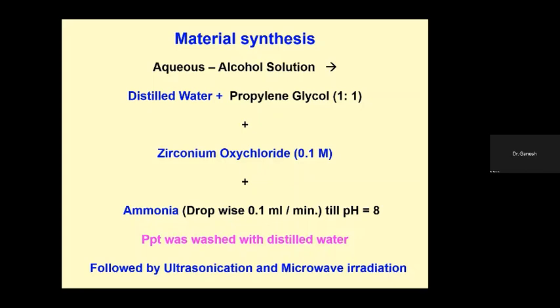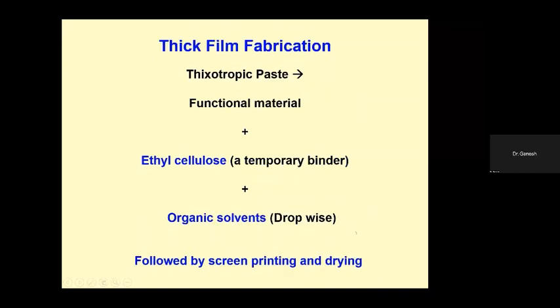If we perfectly manipulate the pH and the concentration of the solutions, then we can get different forms of nanomaterials: nanorods, nanoplates, nanoflowers, nanopetals, and even nanoparticles. So we can achieve different shapes of nanoparticles with different sizes. This is the engineering of nanomaterial synthesis. Then this precipitate was washed with distilled water, followed by ultrasonication and microwave irradiation. Then we get the nanomaterials of a particular shape and size.